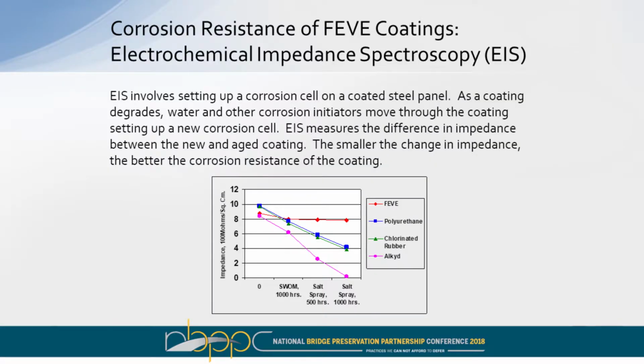We also run electrochemical impedance spectroscopy. You're setting up a corrosion cell with a coating on one side and a salt solution on the other.